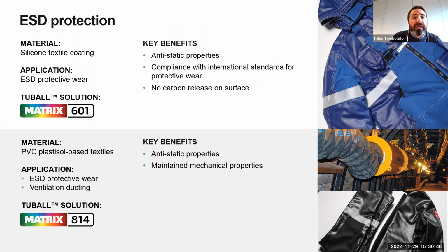What is important is that graphene nanotubes can bring additional properties. I mean, no carbon release on the surface. Graphene nanotubes strongly interact with the polymer matrix, so they will not migrate on the surface, like, for example, carbon black.